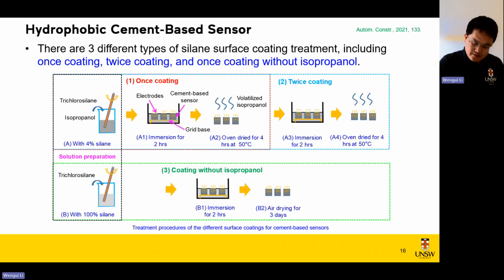To improve the durability and the serviceability of cement-based sensors, here we look at the hydrophobic cement-based sensors with silane surface coating with isopropanol. Here you can see the preparation and the coating treatment process. So here we have three types of silane surface coating treatment, including once coating, twice coating, and once coating without isopropanol.